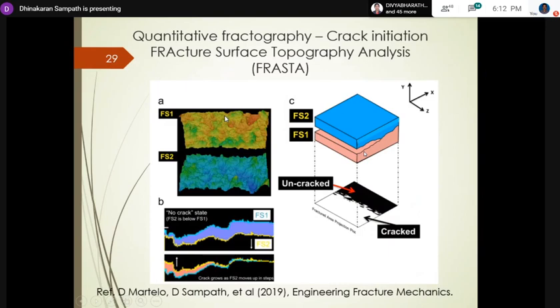So here comes the quantitative fractography, crack initiation. We are going to find the crack initiation point using fracture surface topography analysis. This is the main bit of this study. This was done in the 90s. They used surface topography to replay or reenact the fracture event.